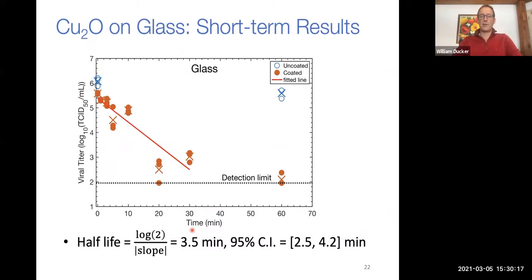Looking at some short-term results, I've just changed the horizontal scale and there's just a lot more data there. The half-life of the virus is in the range 2.5 to 4.2 minutes, so about 3 minutes. So 3 minutes is pretty rapid inactivation of the virus for a coating when you consider that on stainless steel without anything, it's lasting for days. So this is getting down to the type of limit that we were hoping for, where you could envisage multiple people going through some sort of checkout or the TSA or something, and the virus being inactivated in between uses.